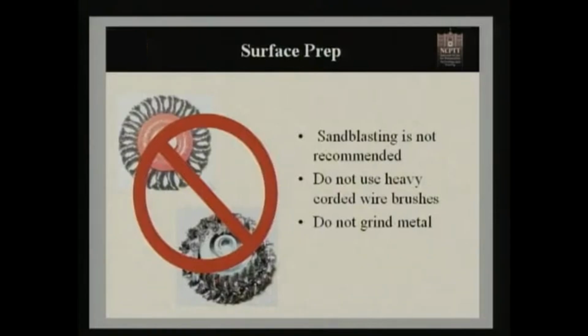Sandblasting is never recommended. Sandblasting actually does a couple things. We can remove too much of the original detail, which we don't want. Sandblasting takes too much of the rust off, leaving a very shiny exposed surface. But also sandblasting can remove what we call mill scale. And mill scale is actually a slightly protective coating that is left on, especially in wrought iron, but also in cast, from the original manufacturing process. It leaves a protective layer on the very exterior of the metal, and sandblasting can actually remove that, making it more susceptible to rust in the future.